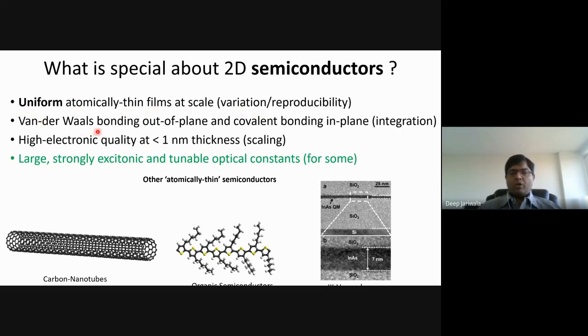And because they have van der Waals bonding out of plane and covalent bonding in plane, they are easy to transfer from one substrate to another, and therefore for vertical integration in microelectronics, they are actually quite beneficial. And finally, the third point, which stems from the first two points, is that they present very, very high electronic quality at thickness smaller than 1 nanometer. This is not true for, say, silicon or gallium arsenide or any other bulk material, but as you thin them down, the material quality degrades.